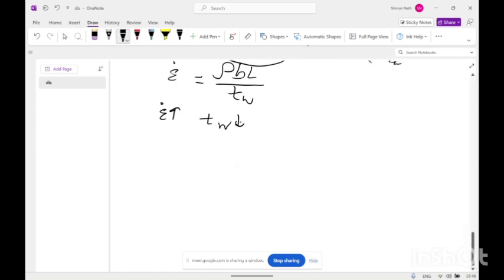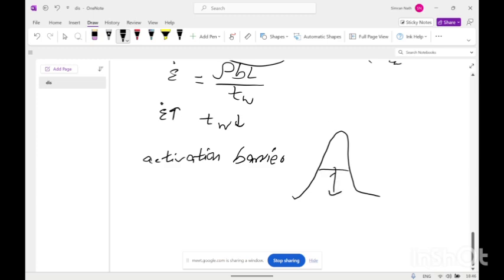So for dislocation movement, the dislocation has to pass the activation barrier. The activation barrier has two components. First is the applied stress, and second is the thermal activation.